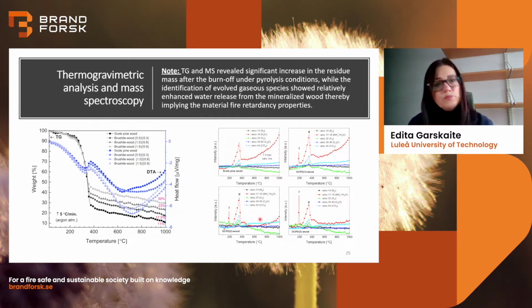So we also recorded thermogravimetric analysis together with mass spectrometry, where gas evolution was checked. And what we observed here is how pure wood behaves, what gases are evolving when you heat the sample and during the degradation, these molecular or ionic species evolving from your sample. And what we observed for mineralized wood is additional evolution of water and also ammonia, which is from this fire retardant material, ammonium dihydrogen phosphate. So basically this implies to us that the material has fire retardant properties.